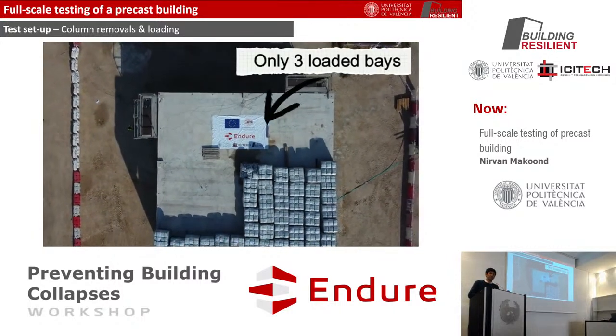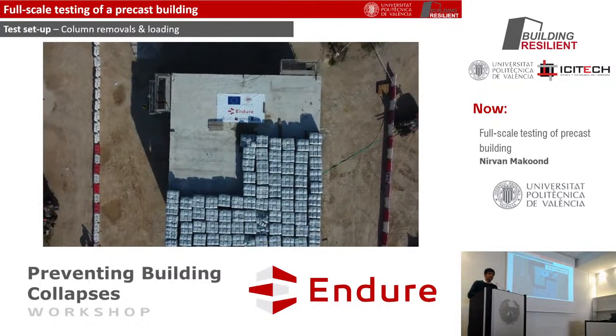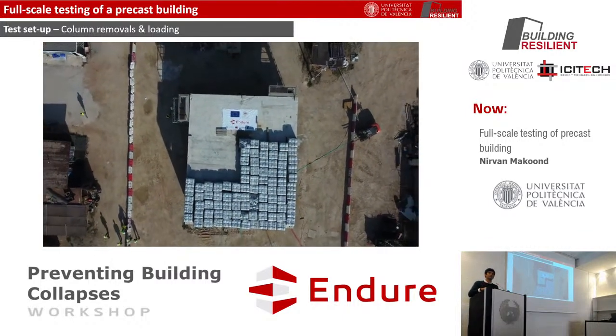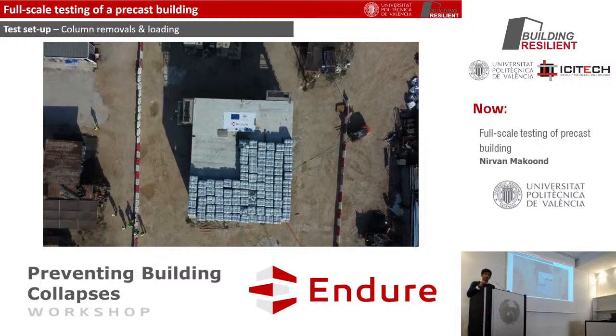So the magnitude of the load, we also decided on it because the first phase of testing was to be quasi-static, and to ensure that the alternative load paths were also valid for a dynamic removal. We basically magnified the load significantly, and at the same time, we knew that this load would also ensure collapse could be initiated in the second phase based on our previous simulation results.